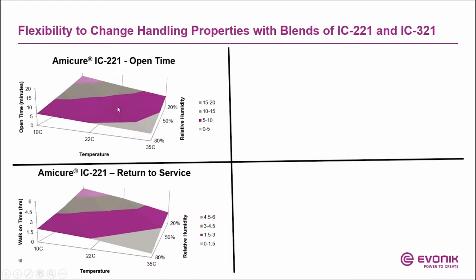So in general, what you're operating in is ambient conditions. So let's say you're at 22 degrees Celsius or 70 degrees Fahrenheit, 50% relative humidity. You can see with Amicure IC221, you're getting this 10 minutes working time, about 2-hour return to service. However, as you go towards higher humidity, you start losing that working time. The film does cure faster, but you need a certain amount of working time to be able to apply it onto the substrate. Otherwise, if you have very short working time, the coating is not going to look good.